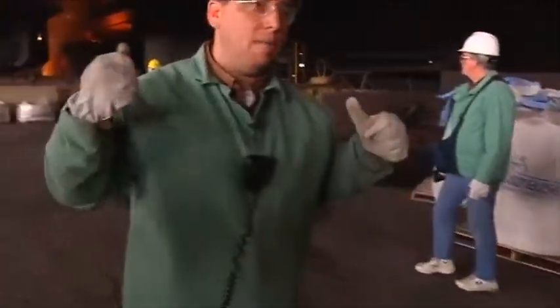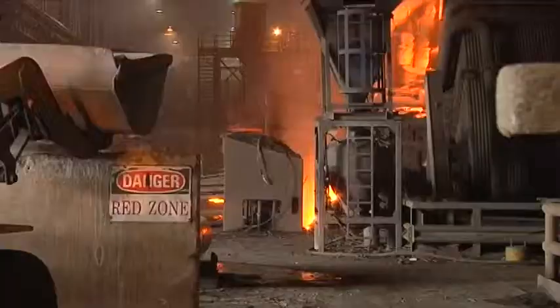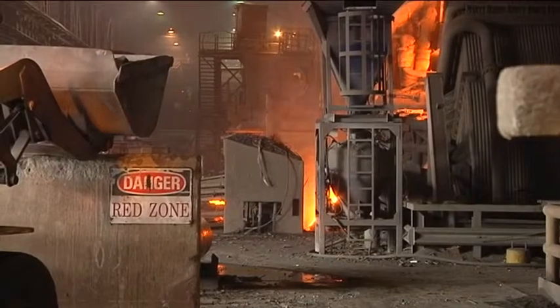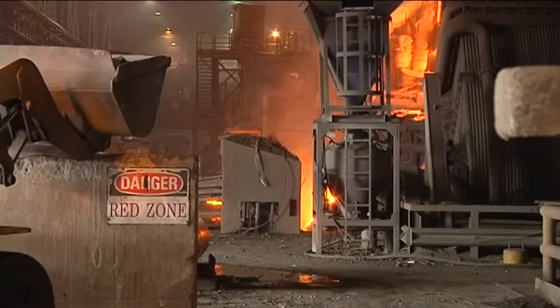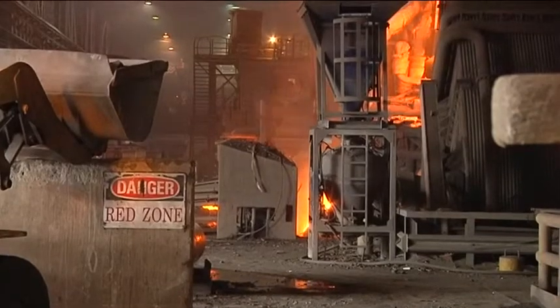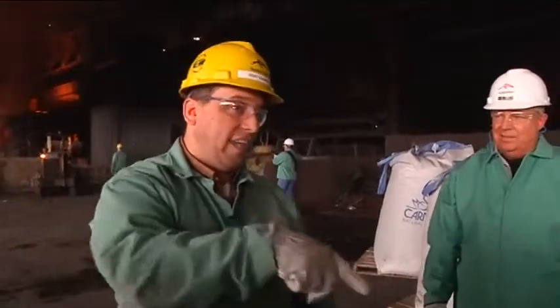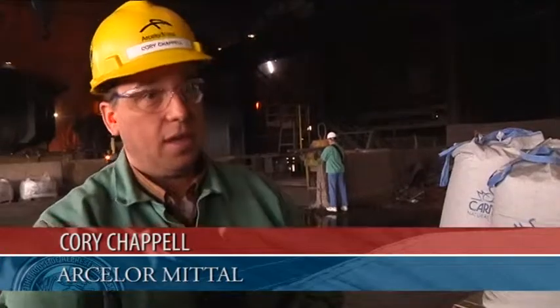What's behind me is the melting furnace. That's where all the scrap goes in, and we melt it down into 150 tons of liquid metal. That siren that you heard just a minute ago, we take a sample in the liquid, we measure the temperature, we measure the carbon, and measure the oxygen. If they're within the range that we need, we tap the heat. Typically, the liquid is tapped out of the furnace right at 3,000 degrees Fahrenheit.